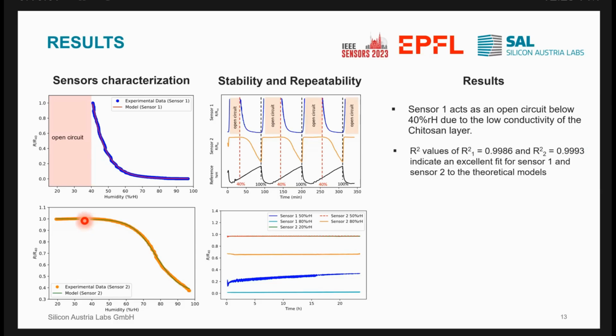When considering the simplified equivalent circuits that have been presented before, so here just with the series resistance for sensor 1 and the parallel resistance for sensor 2, you see that it has a very good fit to the theoretical models, with R squared values of 0.9986 and 0.9993 for the 2 different sensor designs. Depending on the sensor design, a higher sensitivity can be achieved either in the lower or in the higher humidity range. However, below 40% relative ambient humidity is not the operating range of the sensors.